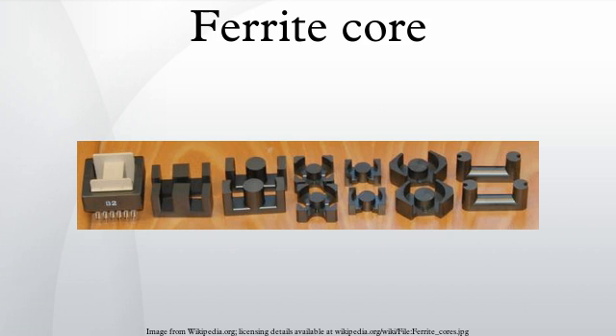Cores can also be classified by shape: there are toroidal cores, shell cores, cylindrical cores, and so on. The ferrite cores used for power transformers work in the low frequency range, are fairly large in size, can be toroidal, shell, or C-shape, and are useful in all kinds of electronic switching devices, especially power supplies from 1 watt to 1000 watts maximum. The ferrite cores used for signals have a range of applications from 1 kHz to many MHz, perhaps as much as 300 MHz, and have found their main application in electronics such as AM radios and RFID tags.